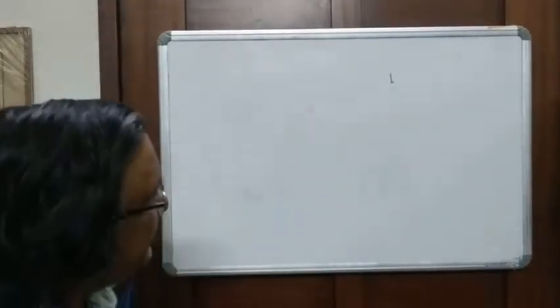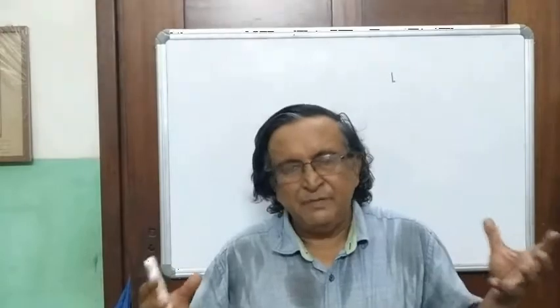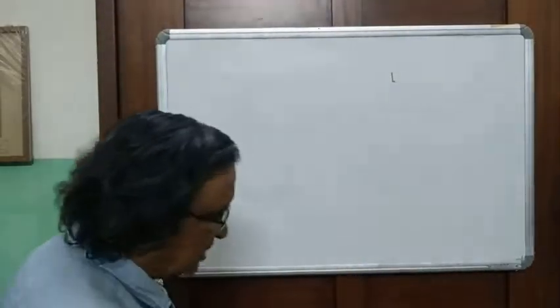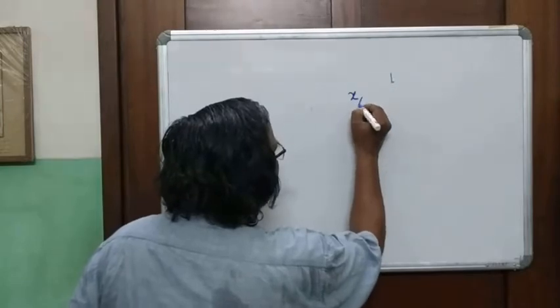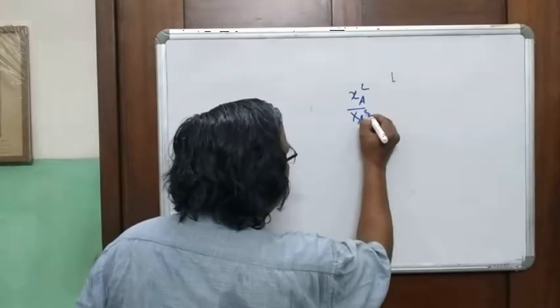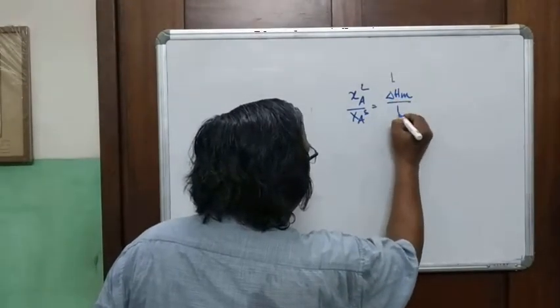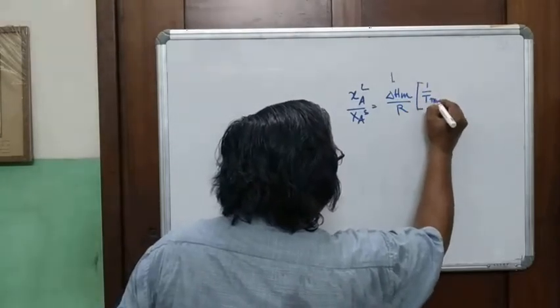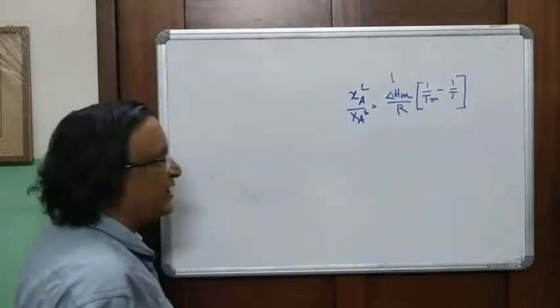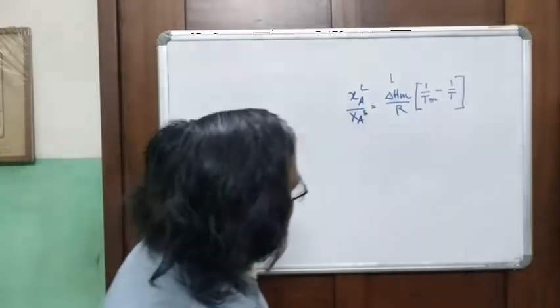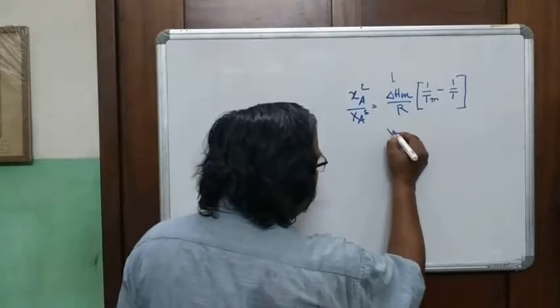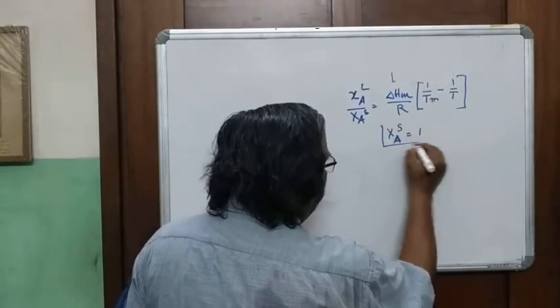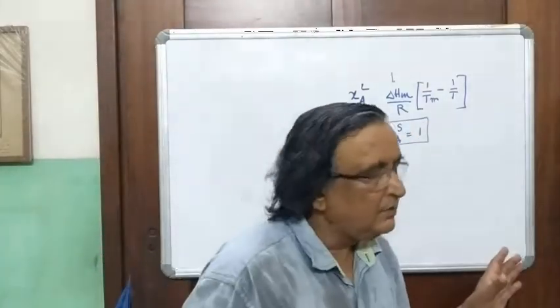Friends, we have been so far dealing with binary system and simple eutectic system where A and B, the two binary components, do not mix in the solid, but they mix in the melt. This we essentially started from this expression which I derived, XA liquid divided by XA solid is equal to delta HM by R into 1 by Tm minus 1 by T. That was our expression of the cryoscopic equation. And here XAS we considered equal to 1. That means whatever solid phases we had, they were pure.